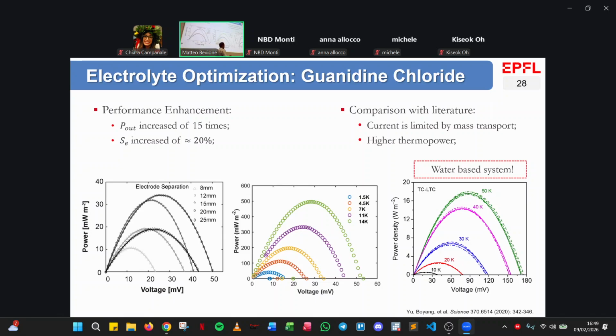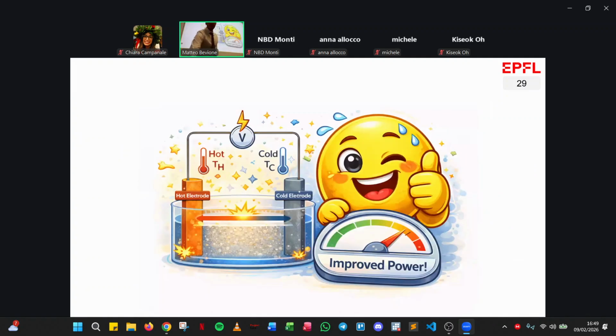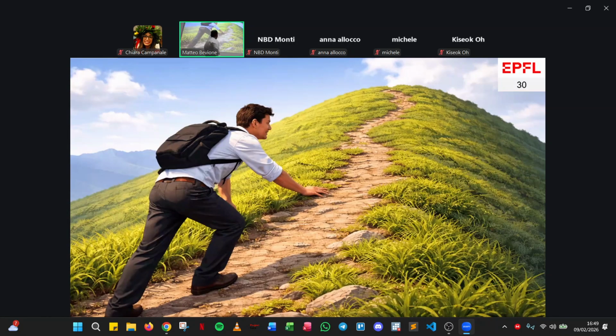The point of this graph here, you see that the scale is much higher, but don't get tricked. The point is that they could fix the temperature of the cold side, so achieve a much higher temperature gradient. In a passive configuration, that's pretty much not possible. You rely on the heat transport throughout your device. So yes, we did it. We could get a very good power output. I could see the top, almost there. But